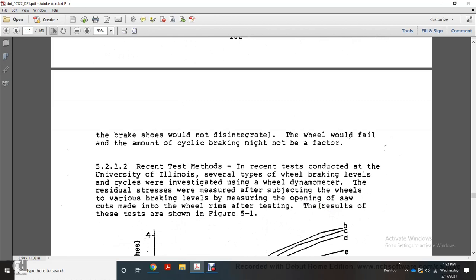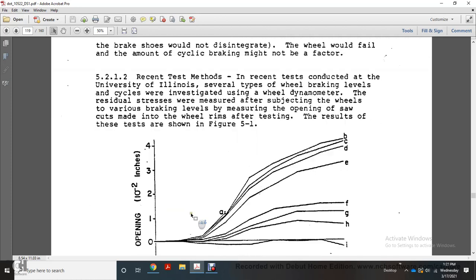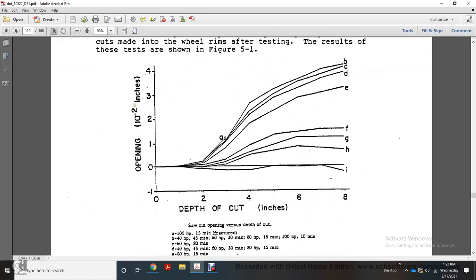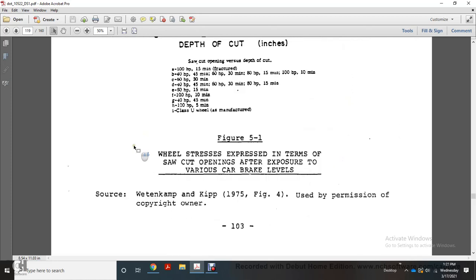The recent tests conducted at the University of Illinois investigated several types of wheel braking levels of the cycle, with the wheel diameter and the residual strength measured after subjecting the wheel to various brake levels, measured by the opening of the cuts made in the wheel rim after testing. The results of these tests are shown in figure 5-1. Opening 10 to the minus 2 inches, depth of the cut in inches 2, 4, 6, and 8, and then you have lines A through B, C, D, E, F, G, H, and I.